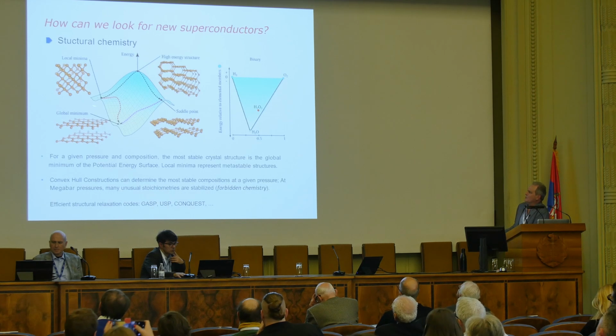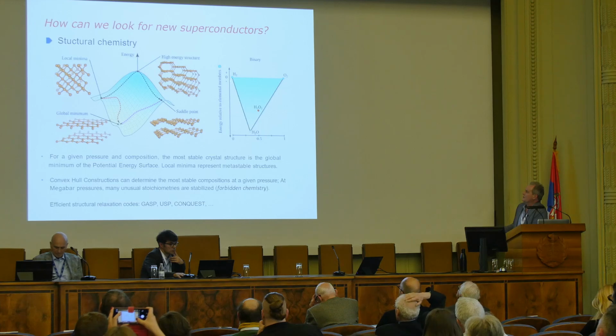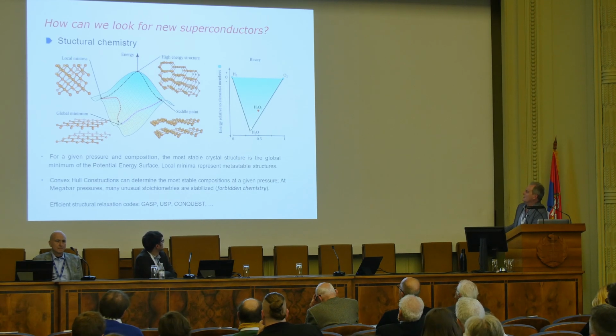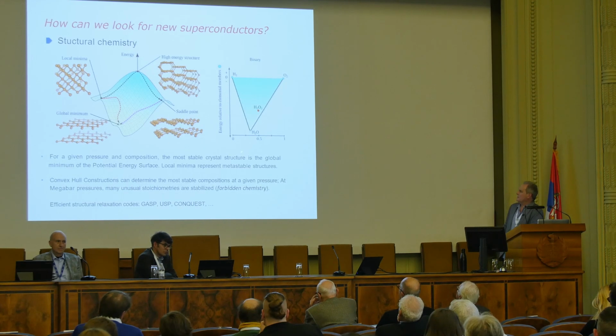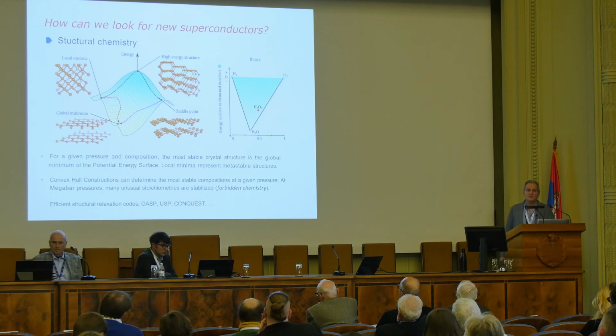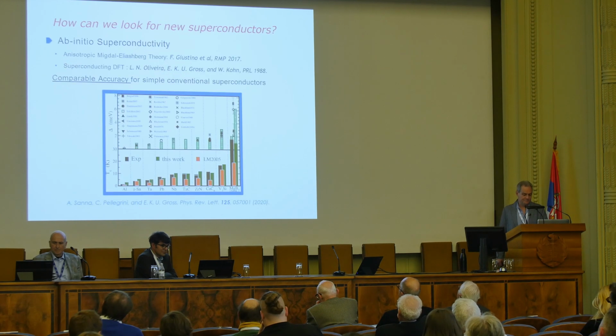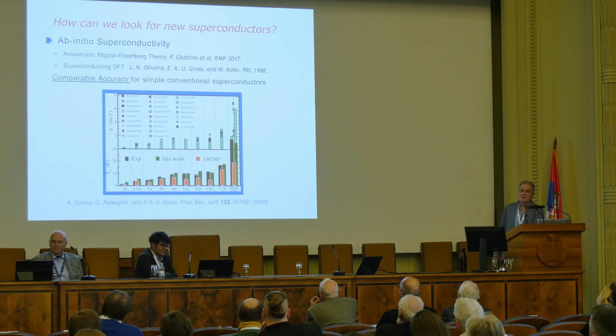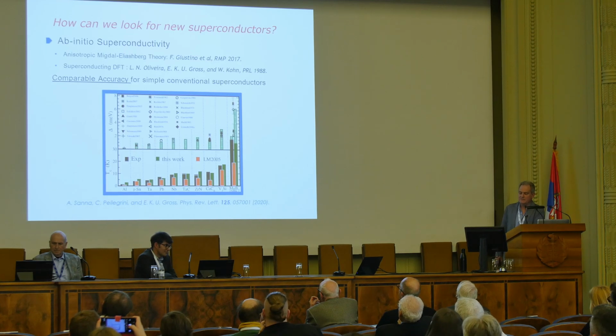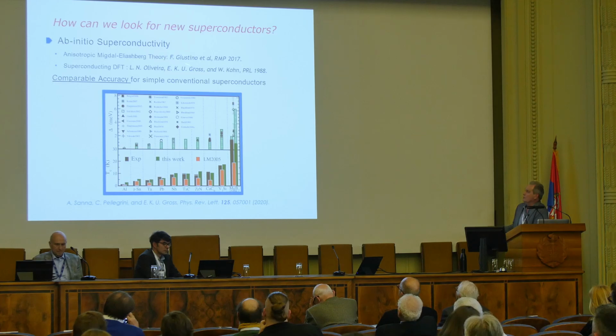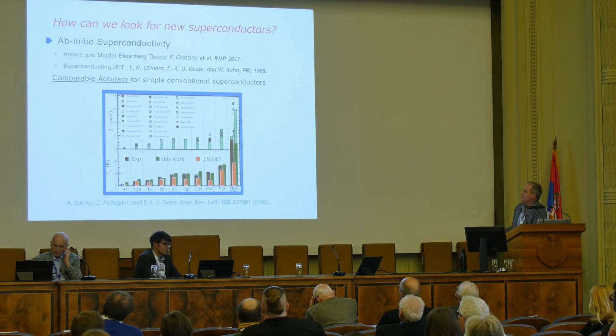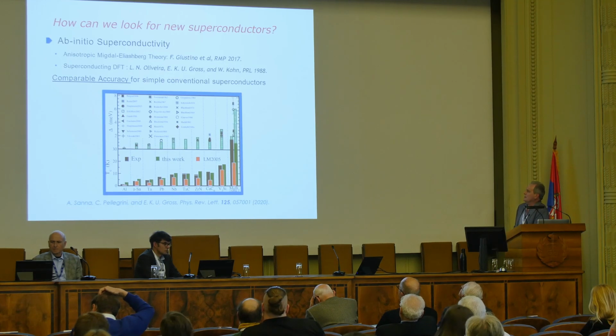The actual kinetics of how you get from one structure to another are very complicated. There is some so-called convex hull where you plot the enthalpy versus pressure here, and there are compositions which are stable, and then there are many up here which are not. So basically you're searching for materials. You can invent stable materials if they're close to or on the convex hull, ideally. At the same time, computational methods for electron-phonon superconductivity have improved greatly. First of all, with the advent of anisotropic Migdal-Eliashberg theory, numerical Eliashberg theory from these authors, the invention of superconducting density functional theory, which is kind of a competitor to the first, by Hardy Gross in Halle.